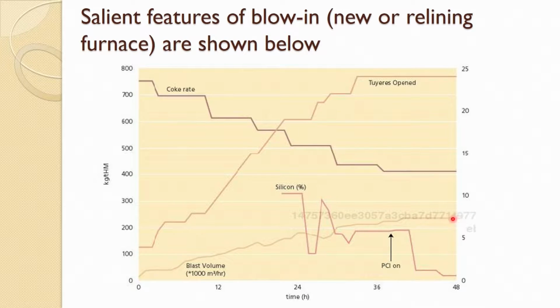It goes in 48 hours to the normal one, and similarly your silicon percent content also fluctuates and reaches its normal value. Your tuyeres open slowly and reach normal operation, and coke rate is also from very high, 750, then it reaches almost 420 or 410 kg per ton of hot metal. So, when these target values are reached, then one can say the furnace has achieved normal operation, which takes almost 2 to 2.5 days.